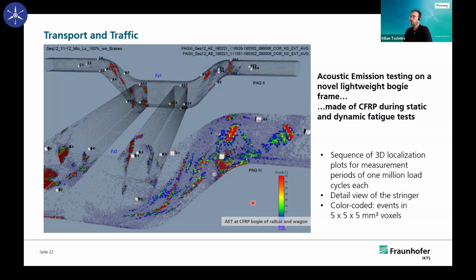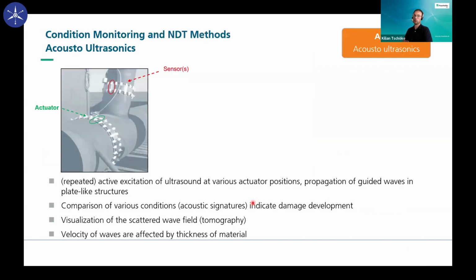Yeah, this is an example for acoustic emission, and another technique using guided waves is the so-called acousto-ultrasonic technique. We call it an active method because we actively excite guided waves into the structure. In general, one can use the same piezoelectric transducers because they are able to excite and to receive signals. And if we have, again, a distributed network, then we can do both.